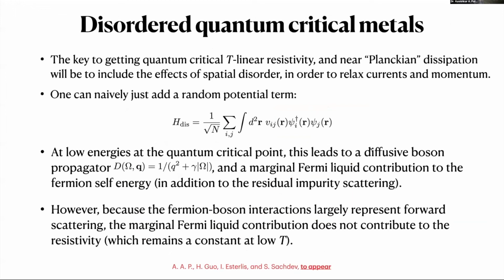So the key to getting some relaxation of momentum and therefore finite resistivity, that I will pursue, will be to include the effects of disorder in order to relax currents. So one can just take the quantum critical theory, and the first way to add disorder would be adding a random potential term to the quantum critical theory, which is written down this way with the large N SYK-like construction. And if you include such a term, this modifies the low energy behavior of the fermions, which leads to a boson propagator at the critical point that has this diffusive form. And then the correction to the self-energy that the fermions get from scattering off the boson is marginal Fermi liquid-like.